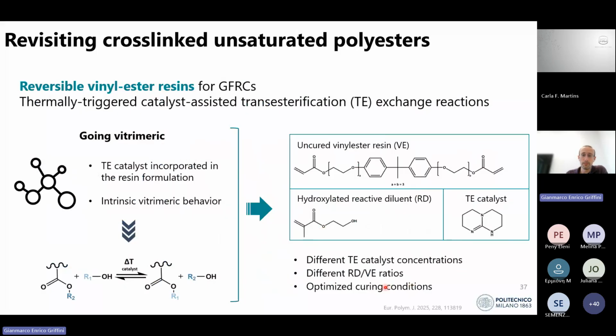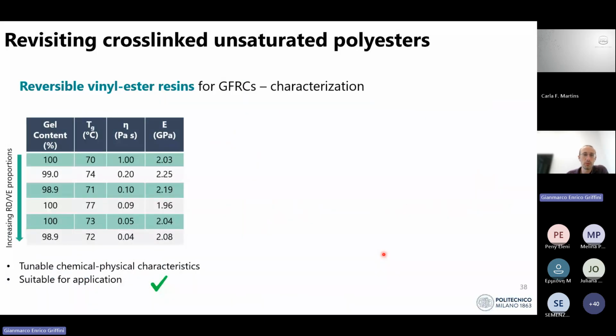So again, we modulated the formulation to obtain different reactive diluent to vinyl ester ratios, and by assessing the thermomechanical response, we also obtain glass transition temperatures which are aligned with what we typically observe on cross-linked unsaturated polyesters, with viscosities which are pretty good in terms of processability. So we could achieve values as low as, let's say, 10 to the minus 2 Pascal second, which are in line with typical viscosities needed for the production of composites through, for instance, infusion.